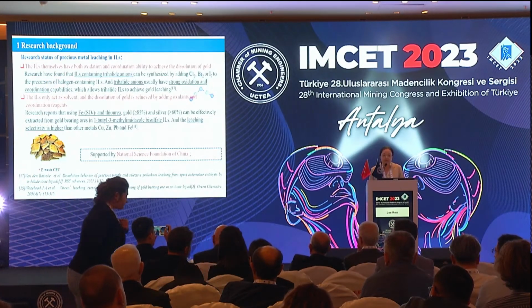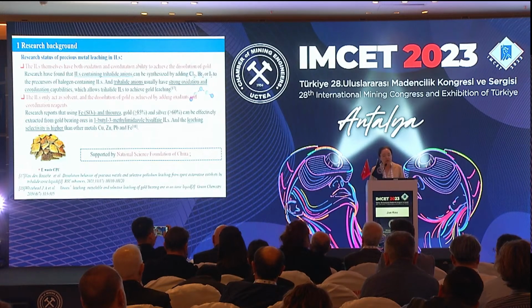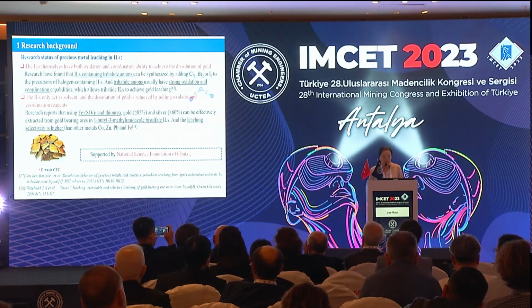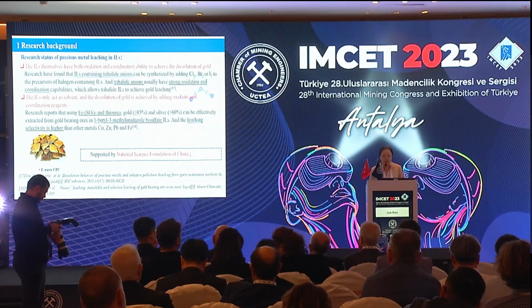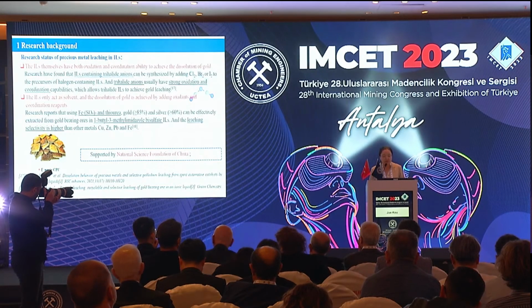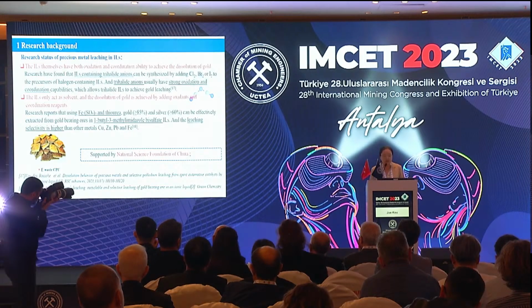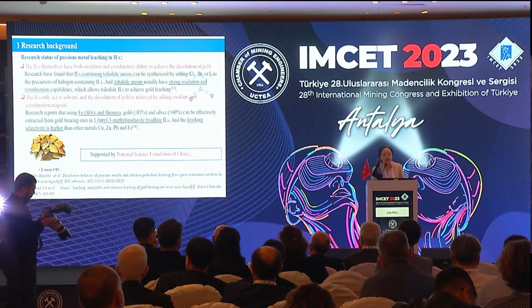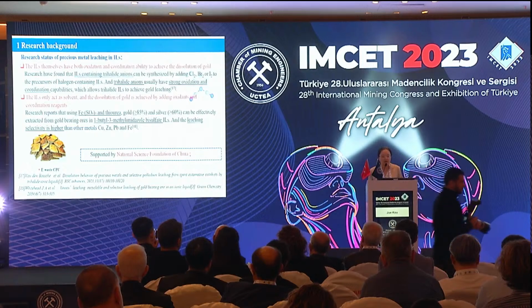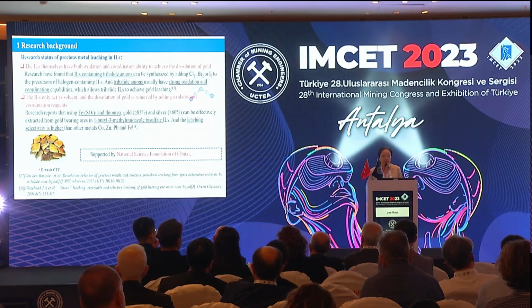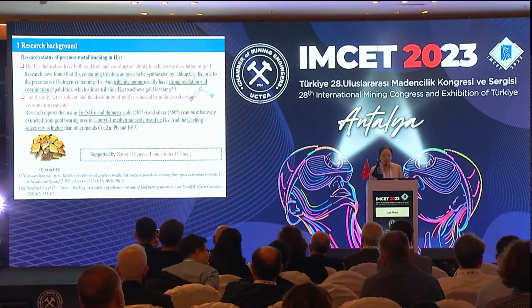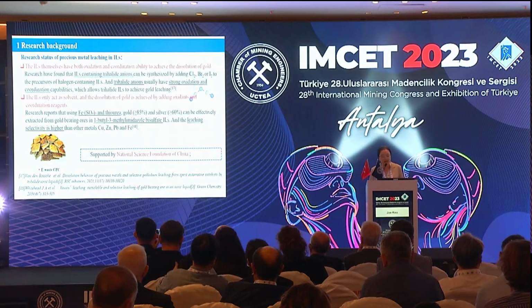There are also some references and literatures reporting the gold leaching performance of ionic liquids. For example, we have this paper from Hydrometallurgy, which can use it to dissolve the gold with strong oxidation and coordination capability. And also, the ionic liquids can be used as solvent. For example, for thiourea gold leaching, we can use the imidazole-based ionic liquid as solvent, not using water, without water in this whole process. And it shows very good selectivity between different metals, for example, gold, copper, zinc, lead, or iron.